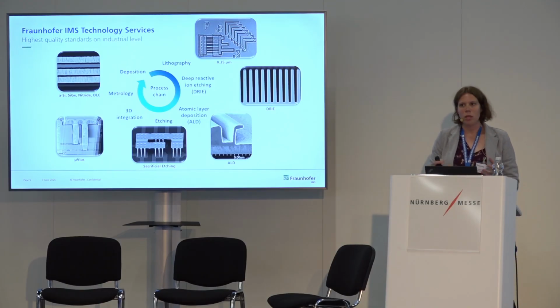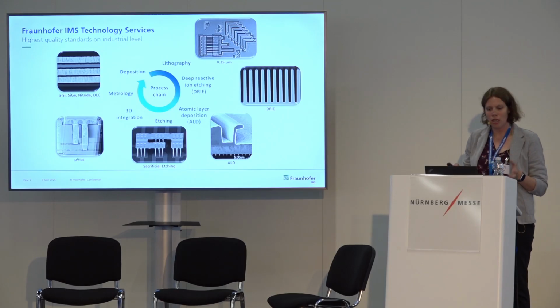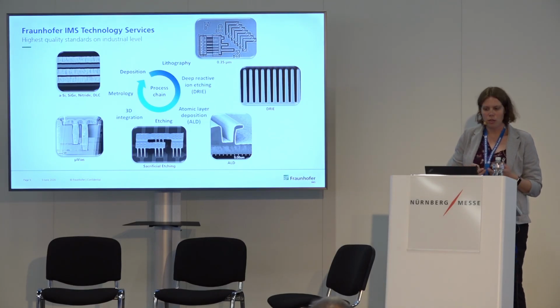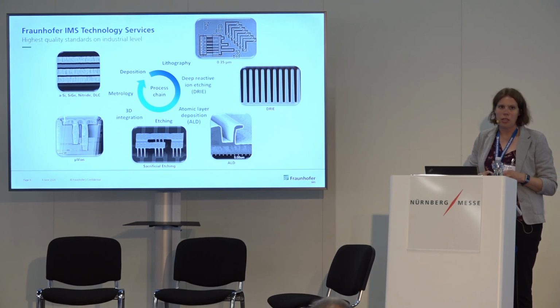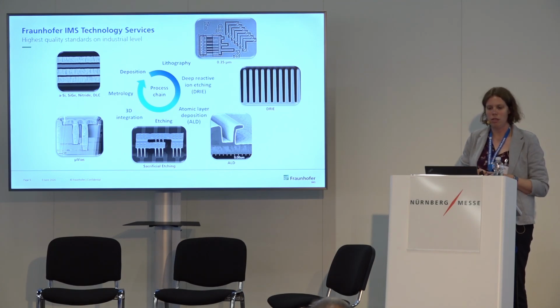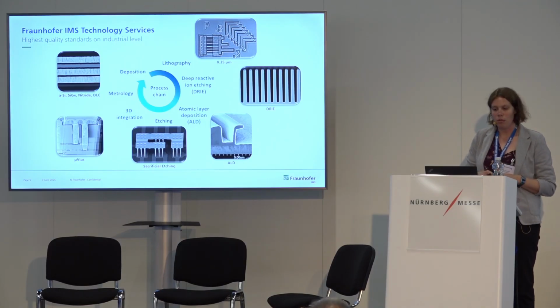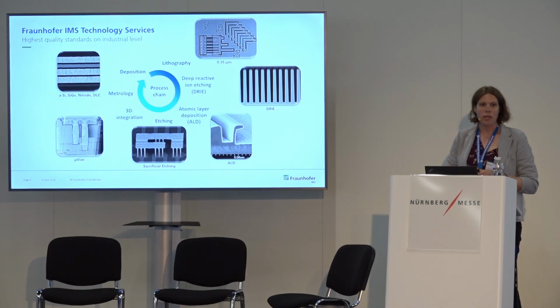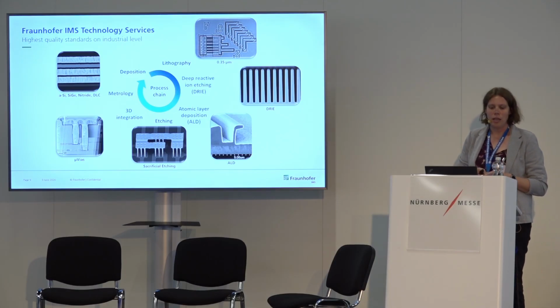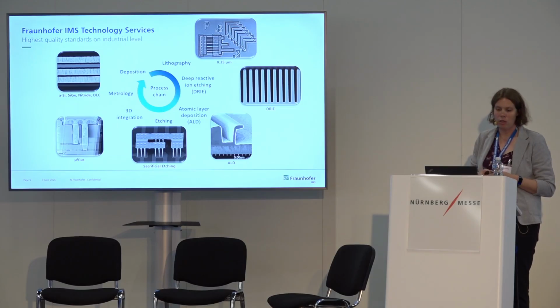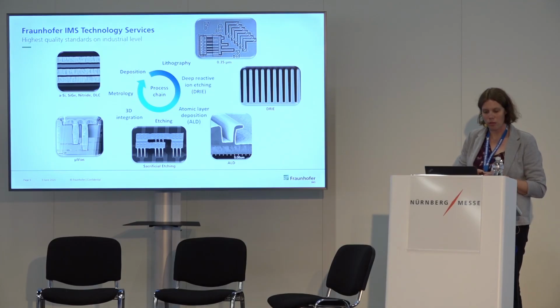In our clean room, we are covering more or less the full process chain, starting with different deposition methods like CVD, PVD. We have lithography. We have also DUV lithography, deep reactive ion etching to get really high aspect ratios in our silicon substrate. We have the field of atomic layer deposition, of depositing really thin layers. We have several etching tools available, chemical etching, but also physical etching, HF etching, for example, and also our patented sacrificial layer etching process to create freestanding structures.